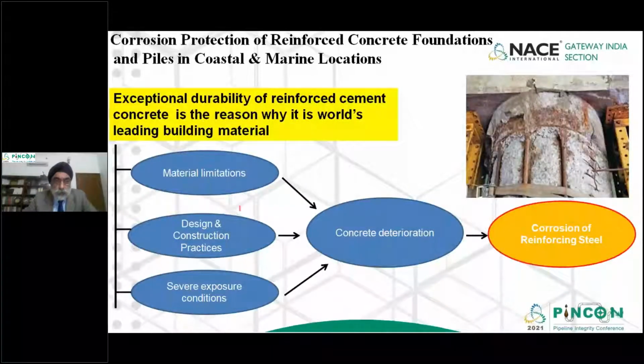As I said, reinforced cement concrete is highly stable because the reinforcement in the concrete becomes passive due to the alkaline environment of the cement. So now in normal cases, the steel reinforcement should not corrode. The cement acts like a coating to the steel rebars which are embedded in it. But due to material limitations, design and construction practices, severe exposure conditions of the soil, wherein if you have a lot of chloride ions which are available, the ions penetrate into the concrete cover and start the deterioration process of the rebars. And as rebar corrodes, its volume increases, it cracks the outer surface of the concrete and allows moisture, chloride ions, and other corroding ions to come in contact with the steel, leading to a rapid corrosion of the steel rebars.